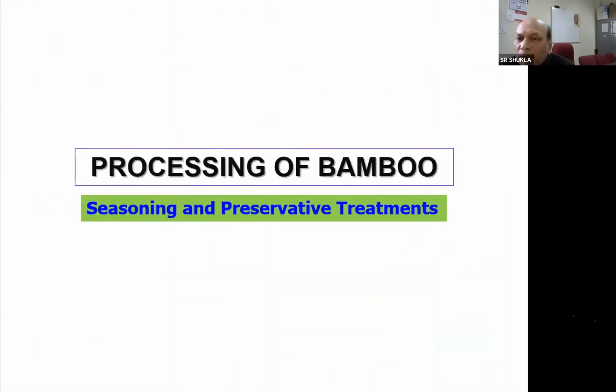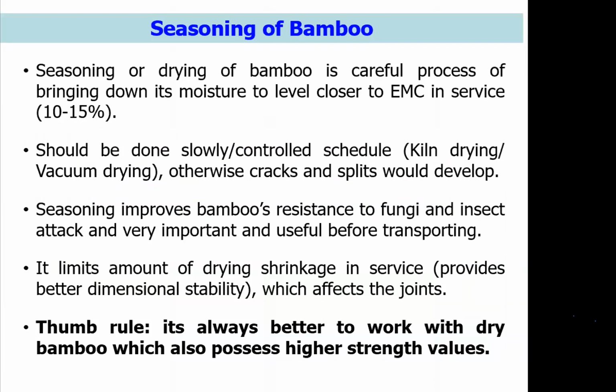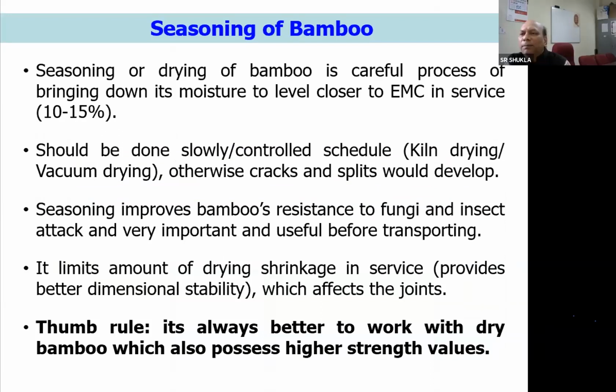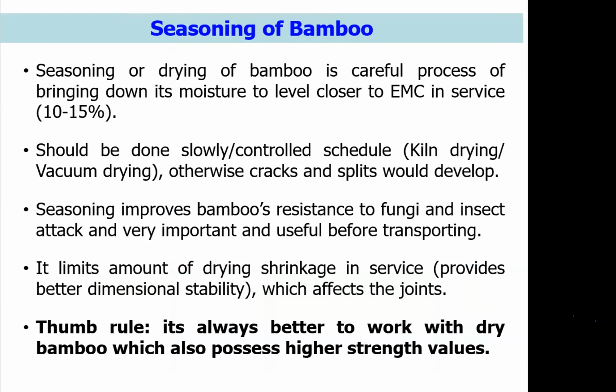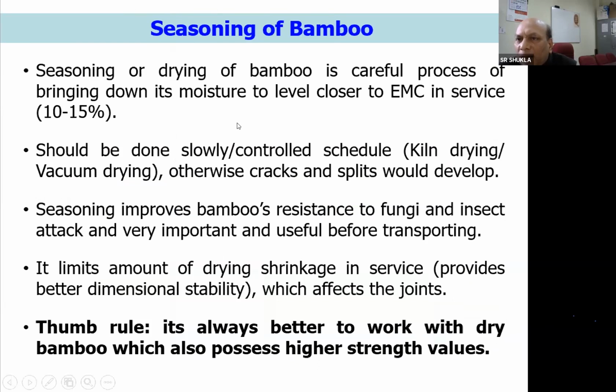So what is to be done to give a longer service life to the bamboo? One processing which has to be done is the seasoning, and another is the preservative treatment. Briefly, I will tell about the seasoning. It is a process of careful and controlled removal of the moisture from the bamboo, because when bamboo is green or when it is harvested, the amount of water present may be quite high, maybe 100% or more than that. So the moisture should be removed in a controlled way and brought down to 10 to 15%. Then the bamboo should be used.